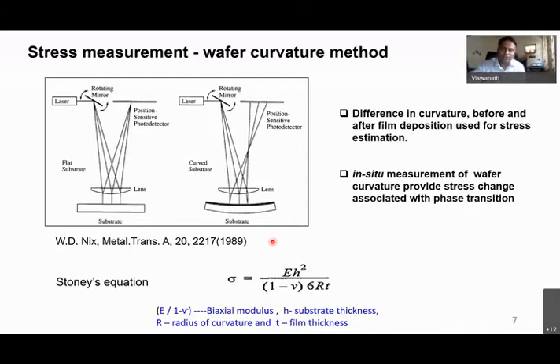So obviously the thin films would impose some stress on the substrate. You can see here, the substrate itself can have a very small curvature. So what do we do for a thin film stress measurement? Before and after thin film deposition, typically we use a laser scanning method to measure the curvature. It's a very sensitive tool I have used for at least several years. And once we know some of the parameters, of course, we need to know. The assumption is your substrate thickness has to be much larger compared to the film thickness.